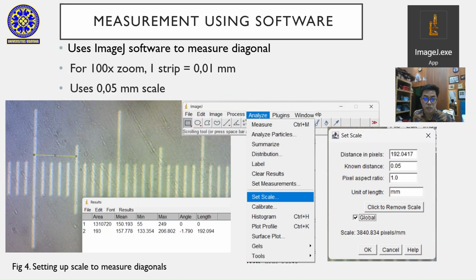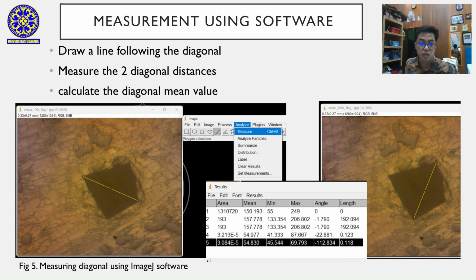The diagonal indentation measurement process was carried out using ImageJ software. First, determine the measurement scale by drawing a line on the scale image and setting the desired scale. In this test, I used a scale of 0.05 mm. Once the scale is set, open the indented image file, draw a line along the diagonal and then click Measure. Calculate the average of the two diagonals at each test point.